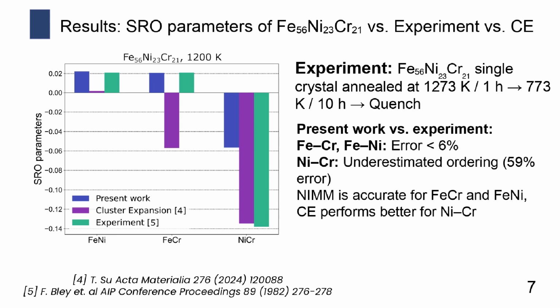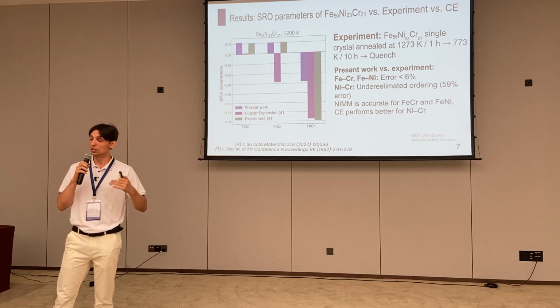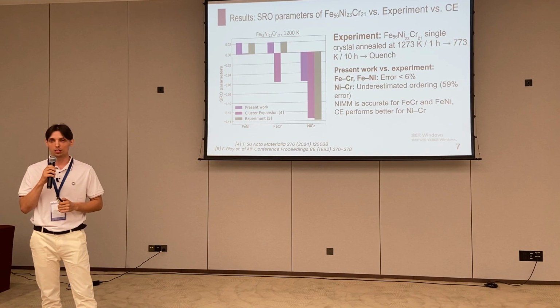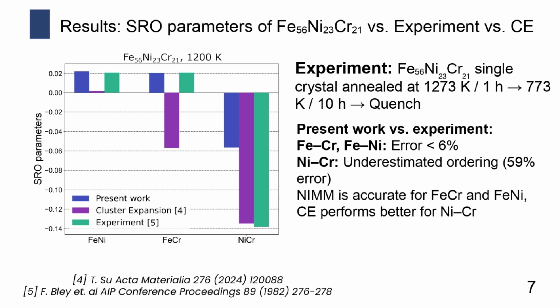So this is the comparison of the prediction using this non-interacting molecular method and the experimental results. We selected the alloy iron 56, nickel 23, chromium 21, because for this system short-range order parameters have been measured experimentally. And the non-interacting molecular method predicted that for the iron-nickel pair and iron-chromium pair, the error of the calculation is less than 6%, which even outperforms the cluster expansion method, which is much slower. Also, the calculations show that the nickel-chromium pair has high ordering. However, the method underestimates it, with 59% error. However, it means that the method is reliable and can be used to conclude the main tendencies in the system.